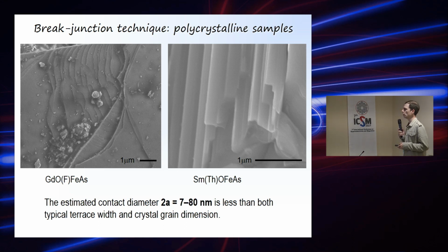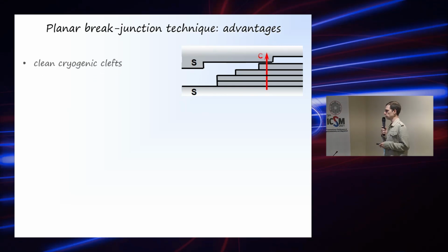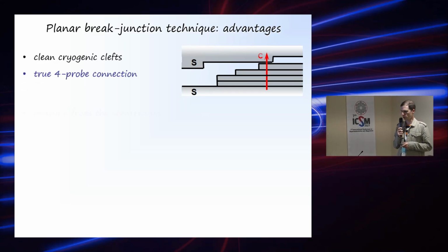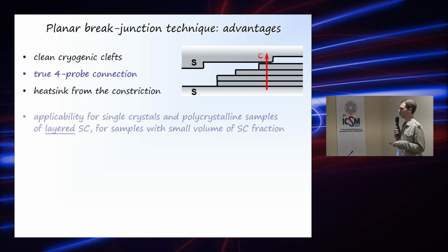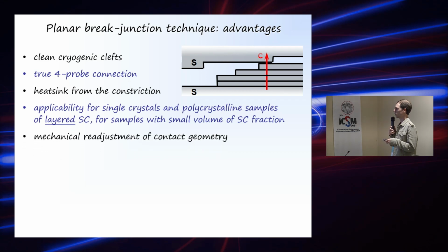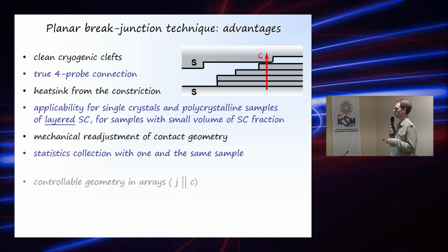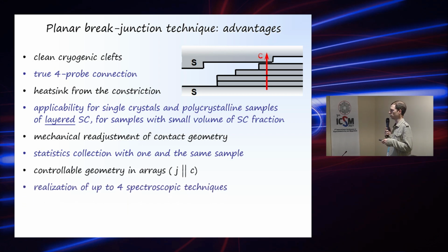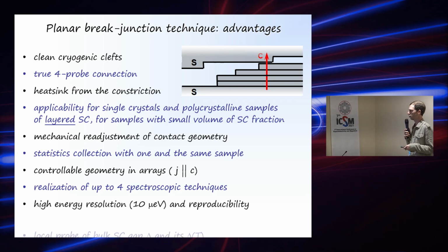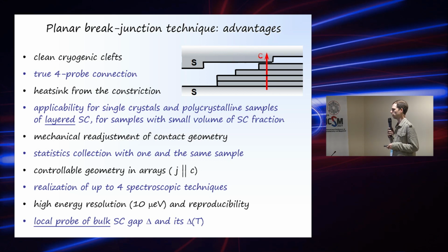at some terrace. So the planar break junction technique allows working also with layered samples, and it produces a good heatsink from the constriction, because this point is connected with the bulk from the upper and from the lower sides. It's a good heatsink. It is possible to mechanically readjust the contact geometry. Several spectroscopic techniques, I mean Josephson, intrinsic Josephson, Andreev, and so-called intrinsic Andreev spectroscopies, give the local probe of the bulk superconducting gap when we work in the bulk of this step.